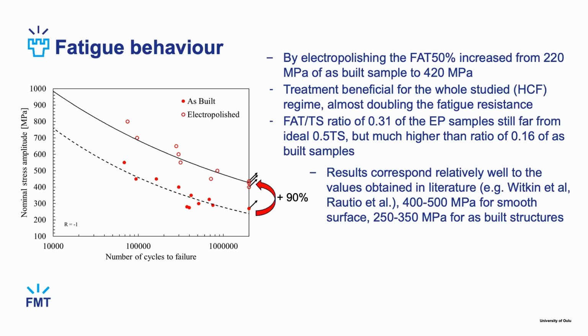The results that we obtained here correspond relatively well to the values obtained in the literature. There are a couple of papers, for example, and for the polished or machined condition with smooth surface, they get roughly 400 to 500 megapascals with this kind of heat treatment. This is perhaps a slightly lower value for the as-built one, but this is always dependent on the machine itself. So you might have a slightly rougher surface, or you have the downskin effect, or whatever there is that can lower this value or change it. So the deviation is usually higher in this one.